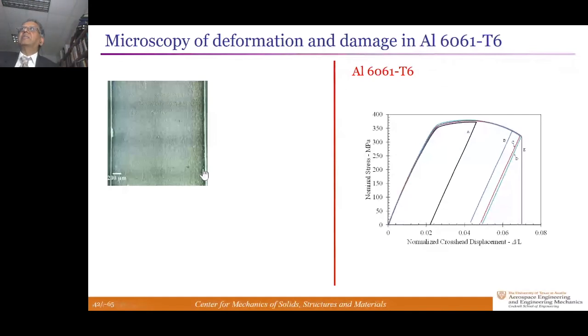And eventually at E, it fails, but this time the failure is somewhat different from what we saw in the copper. Again, there is plane strain localization, and so these bands along which the failure occurs are localized along that orientation. But they fail by a different mechanism. If you look on the surfaces of those fractures, they're fully dimpled. They say that there's a void growth and coalescence mechanism by which this occurs.